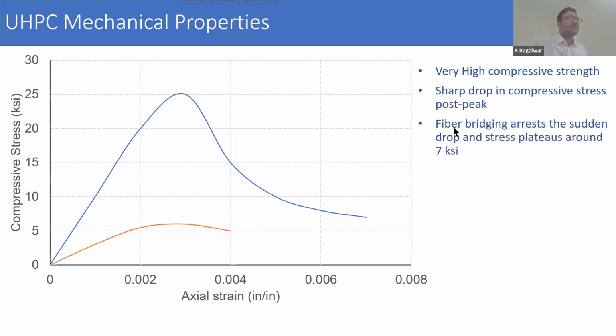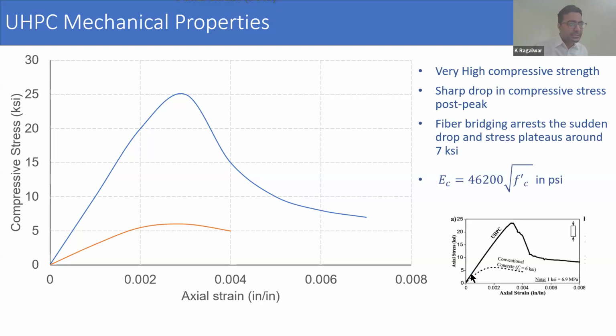Fiber bridging capacity arrests the sudden drop, and the stress kind of plateaus around 7 KSI. So you would see in this plot, compared to the conventional concrete 6 KSI plot, that UHPC is almost linear, then it drops suddenly and kind of plateaus. Okay.